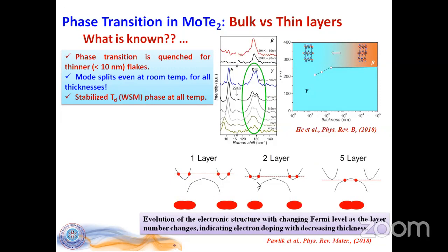Okay, so now there is another article, again a theory, which says that as we thin down, there are inevitable defects, the tellurium defects that are formed, and that defect leads to electron doping in the system. So that is explained in this article: due to exfoliation, tellurium deficiencies occur and lead to electron doping, so they would have achieved an electron-doped system, and that is why they could see the Td phase at room temperature or at any given temperature.